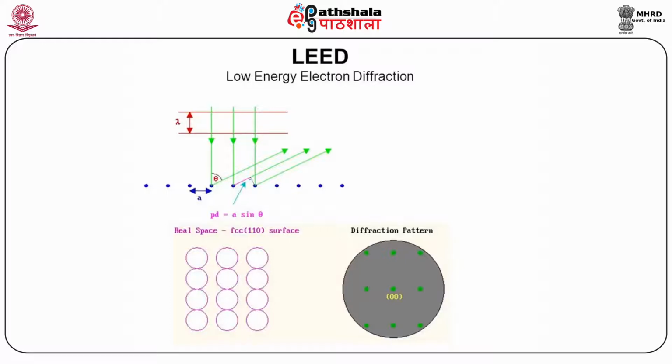The growth of NiO layers on nickel. The LEED patterns of oxidized nickel surfaces, however, mostly indicate the presence of a rather imperfect NiO film on top of nickel, which might result from the large lattice mismatch of nearly 20% between nickel and nickel oxide.